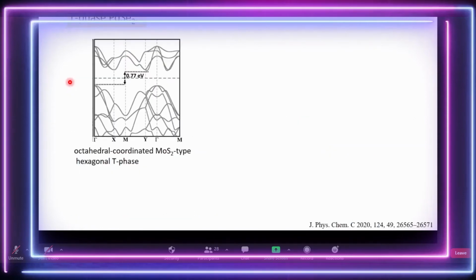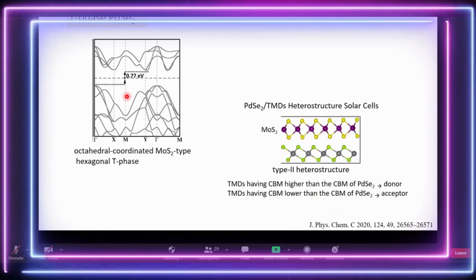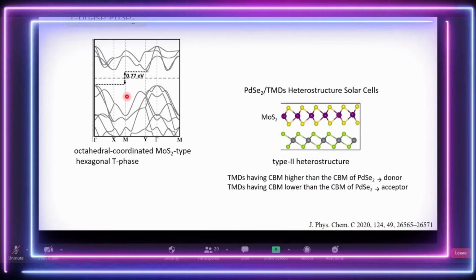Then what you do is a typical band structure calculation to see what exactly it is, and we find that indeed it has a gap, but the gap tends to be an indirect gap, because if we look at the gamma point, the direct gap is much higher than the indirect one. So it's about 0.8 eV. If you recall, the solar absorption is at its maximum at 1.3 eV, but here the gap is only 0.8 eV.